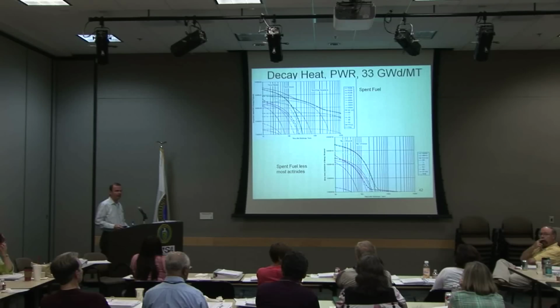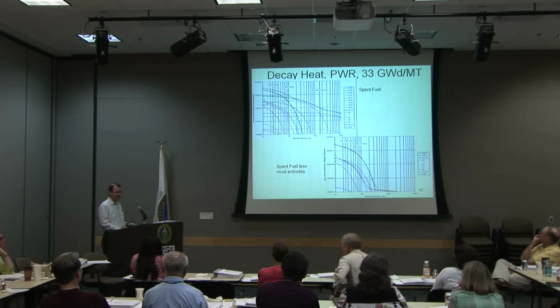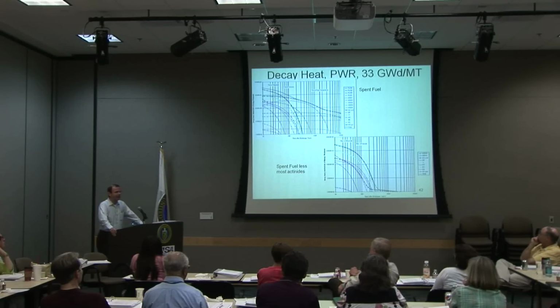Well, you're talking about different types of radioactivity, because initially you got a lot of gamma, right? Yeah. And then with the uranium, plutonium stuff, you got alpha. Yeah, the radioactivity profile changes with substantial drops in gamma rays after 300 years because of the cesium-137 in particular. Right. The actinides build in with, or stay longer, I guess is the better statement, with alpha emitters, and there are some that have a significant or noticeable amount of gamma. It's not like cesium-137, but they have a significant amount of that. Americium-241 can be sort of nasty, and a few neutrons floating around there.